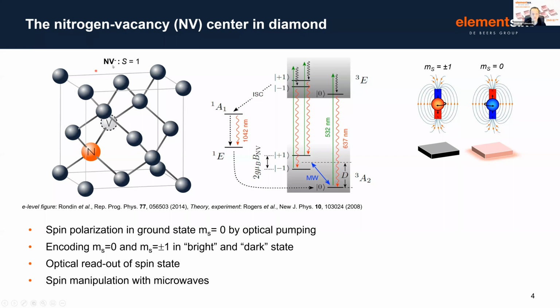If we have this defect in the negative charge state, we have a spin of 1. Now, when we look at the spin state structure of this defect, we can spin polarize the ground state, i.e. create these defects in particular levels in the ground state by simply optically pumping this system with a green LED or laser. One of the other critical factors of the NV center is we can actually encode which spin state we live in, or read out the spin state that a particular defect is in, by measuring the amount of luminescence that this particular defect gives off. Essentially, we see a difference depending on whether it's in one of the plus or minus 1 spin states or the zero spin state in the ground state. So we can optically read out the spin of the defect.